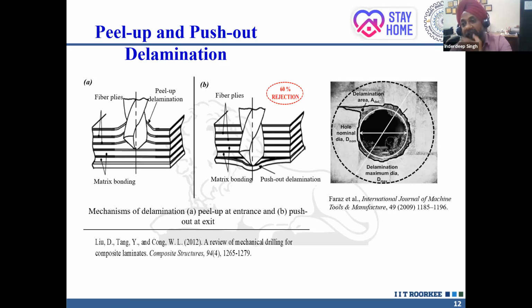If you have a very high feed rate or a very low feed rate, it is going to affect the drilling performance in the laminate. If the feed rate is very high, it will be kind of an impact and the thrust force will be high, and if the thrust force is high, the bottom layers will open up and they will cause the push-out type of delamination, and 60% of the holes will be rejected. If you go very slowly and the feed rate is extremely slow, your productivity will be less. You will take maybe an hour to make a hole, so nobody would like to spend that much time.